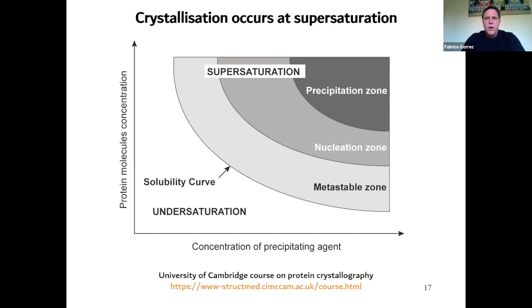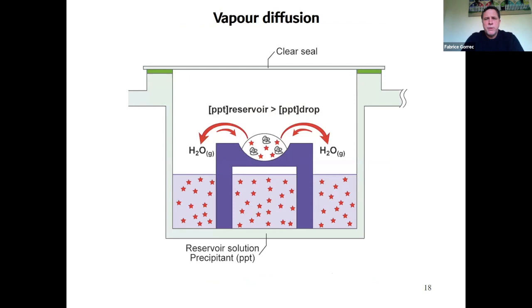One thing that you want to remember from this graph is that the crystals preferably grow in the metastable zone, which is at a lower saturation level than nucleation. While all the methods are based on steadily increasing the saturation, so it's a bit contradictory to the method. So here is the main representation of the main method, which is the vapor diffusion. So basically, you have a chamber with a reservoir with your condition, which contains at least a precipitant. And you will mix this condition with the sample to form a droplet on top of this reservoir.